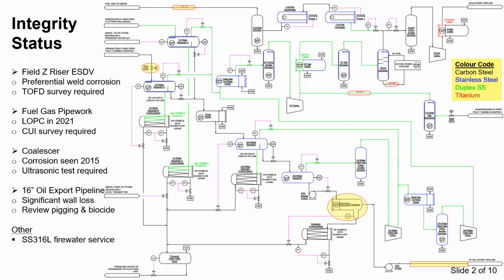Lastly, on the diagram is our 16-inch oil export pipeline. Previous inspection data shows significant wall loss, which has been identified through previous pigging campaigns. The wall thickness is now half of the original design, and that's resulted in the maximum allowable operating pressure of the pipeline being reduced over time. To prevent that being reduced further in future, we would recommend reviewing the pigging routine, potentially doing biannual pigging rather than 5-yearly. And also to start injecting biocide, as it's likely due to water dropout in the line with the lower production rates and velocities, which have then caused the corrosion within the pipeline.